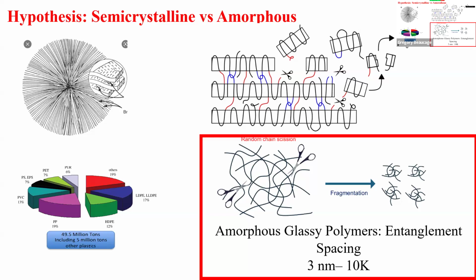Now, the characteristic size of that lamella, the thickness is going to be 10, 20, 30, 40, 50 nanometers, but the width is going to be microns. You're following along. Now, the crystal, that surface tension, right, it turns into wax, right? And you have polyethylene, wax is like lamellae that aren't put together. Correct. Or some kind of graphite. Lubricant, right? So it isn't exactly, you can get graphene from graphite